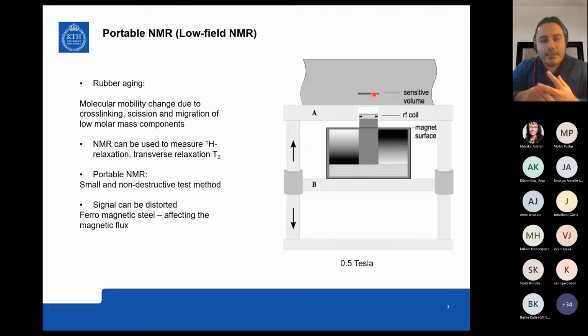The image you see to the right is a schematic of the NMR mouse. It's a commercial name, the mouse, but essentially it's a low field NMR sensor. The functionality of this sensor has a lot of physics behind it, but the easy explanation, at least from the side of a chemist like me, is that we have this stand, and then we have an elevator device, so to say. On this elevator device, we have a permanent magnet. When you have this permanent magnet, you're going to have a magnetic field which is more or less constantly around the magnet. So it's quite straightforward. And on top of the stand, we place the sample.